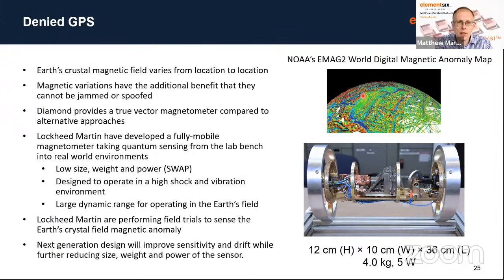So we've been working with Lockheed Martin over the past few years, and they've developed a fully mobile magnetometer which takes advantage of this effect, where they can basically produce a low SWaP system. So this is an image of their system. It's a 4 kilogram system that uses 5 watts of power, and it's designed to withstand high shock and vibration environments. The big advantage of diamond in this is that you have a vector system. The fact that the NV defect has a particular crystallographic orientation means you're able to get a true vector signal compared to other technologies. And they're currently trialing the system as a denied GPS system.